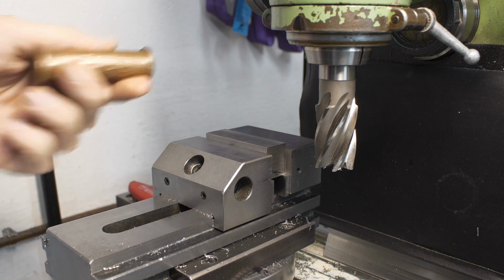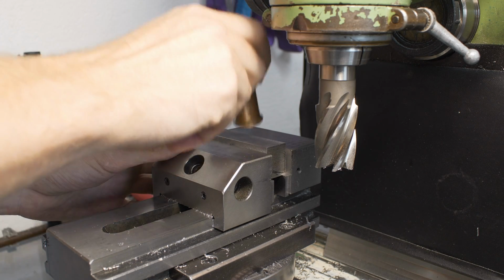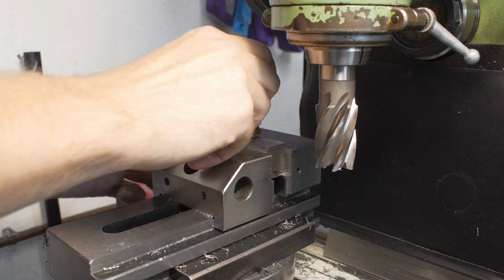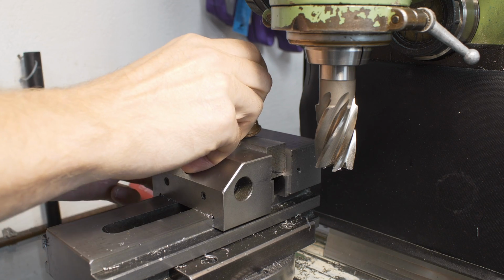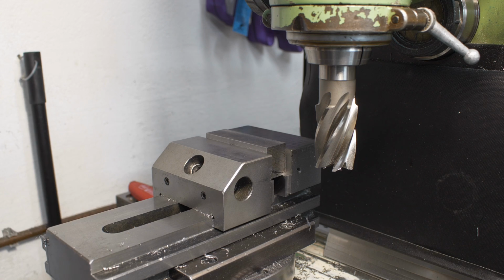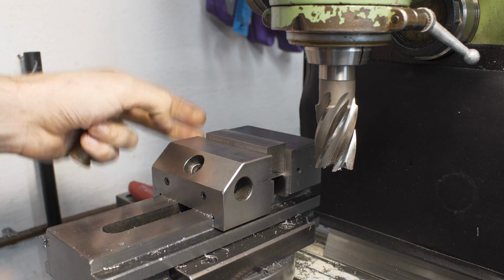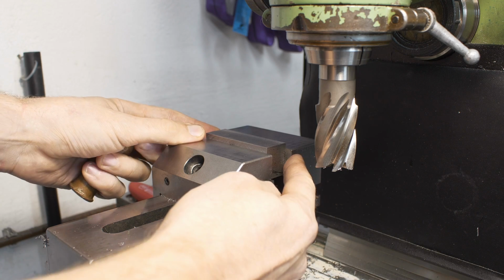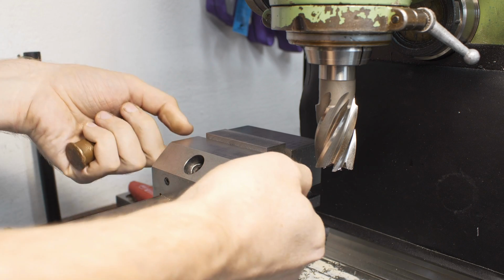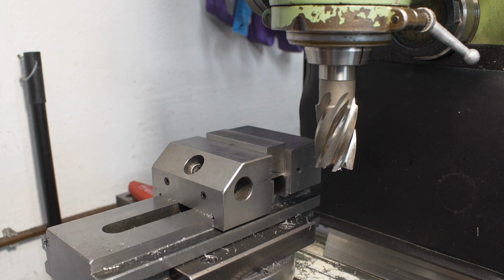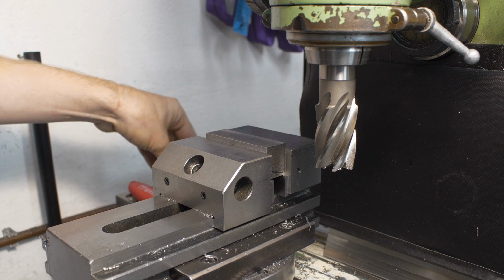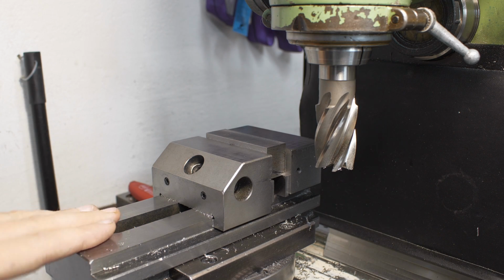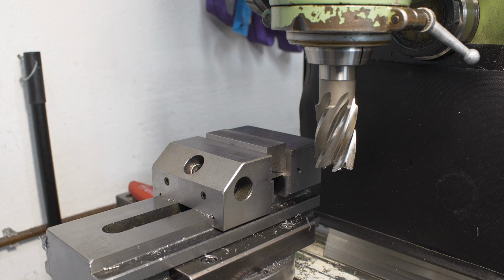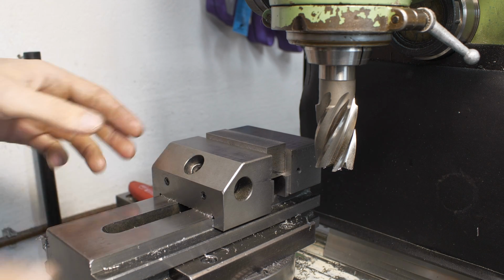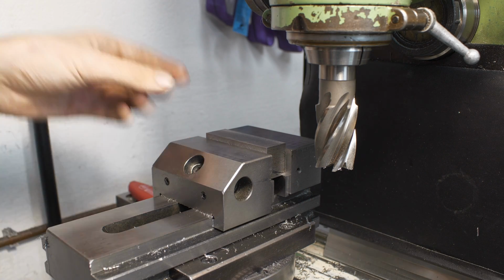But also notice how I use the copper drift when I knock the part down. I'm not letting it bounce off, I'm doing this, I can't exactly describe what I'm doing, I'm just hitting and not letting it bounce back. Also, if you hit the part in the vise strong enough with a rawhide mallet, for example, you might even get the part to bounce off the parallel despite being clamped. I have seen that numerous times. You hit it hard enough and the parallels just get loose again. I don't want to do it here because I have the vise on the indexing head and I don't want to beat it to shreds. But I suspect most people have noticed that behavior at least once in their time as a machinist. So use the force input in your part to your advantage to seat them, and use it mildly, not to lose precision.